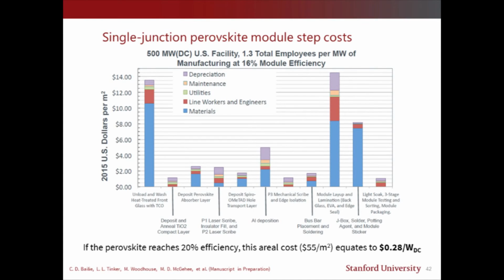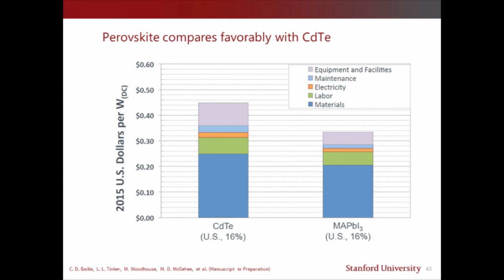while there are three large columns that stand out on this plot. And these three large columns have to do with the front glass sheet, the back glass sheet, and everything else that is common to a module. Meaning that even though we have minimized the cost of depositing the absorber and surrounding layers and defining these cell interconnections, there is a price floor that we are reaching due to the necessary components of a module that at the moment we cannot do without. And the consequence of this can be seen in a direct comparison to cadmium telluride, which is the perovskite's closest competitor.